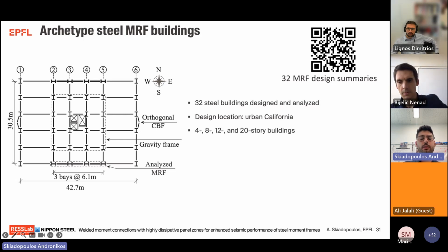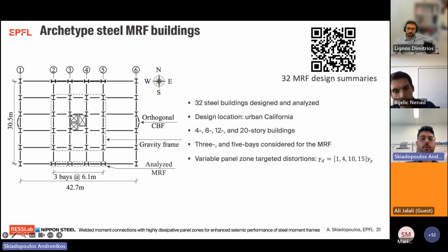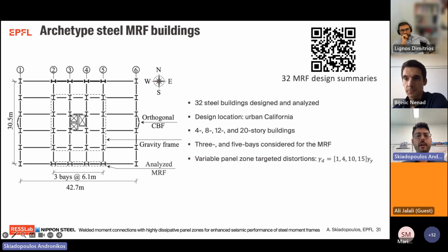4, 8, 12, and 20-story buildings were designed, and both 3 and 5 bays were considered in the moment resisting frame. And with regard to the panel zones, we targeted the panel zone design to 1, 4, 10, and 15 times the shear distortion at yield. And note here that the last two values violate the current seismic norms. We made all these designs, and they're available publicly, and you can find the design summaries in the given QR code on the top right side of the slide.